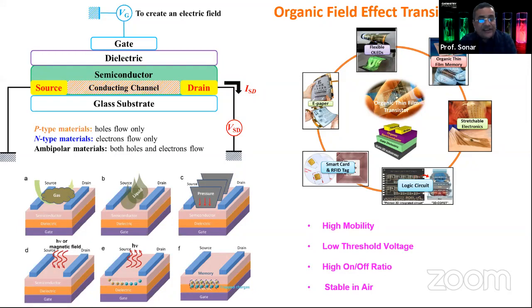It means that in future display devices, you don't require a special backplane transistor circuit to run your OLED, but rather your transistor itself can emit light, which is a very new kind of state-of-the-art device people are looking at. Even for CMOS type, or this photo detector, the cameras which are utilized for low light conditions, taking pictures and all, you require the photo detector. So the transistors can be a very good photo detector. They can detect in presence and absence of light how the current varies. And they can also be useful for memory devices, where you deliberately put some nanoparticles that act as a trapping site where the charges get trapped, and then we can read in and read out the memories where the charges get stored via hysteresis.